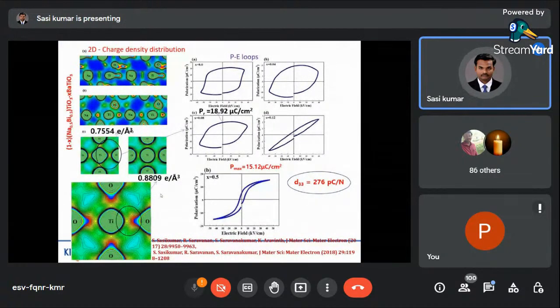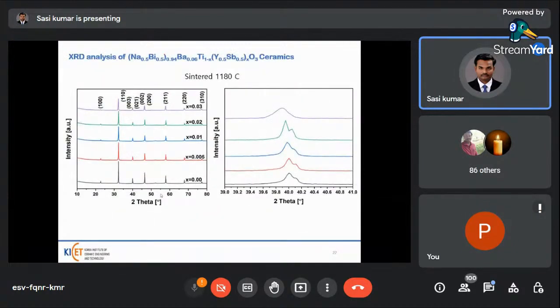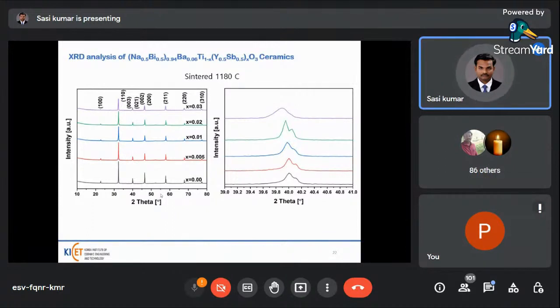The covalency between the Ti and O ions mainly plays a main role in the ferroelectric and piezoelectric properties. So another lead-free piezoelectric ceramic is sodium bismuth titanate, doped with barium atoms, and the Ti atom is modified with yttrium and Sb atoms.